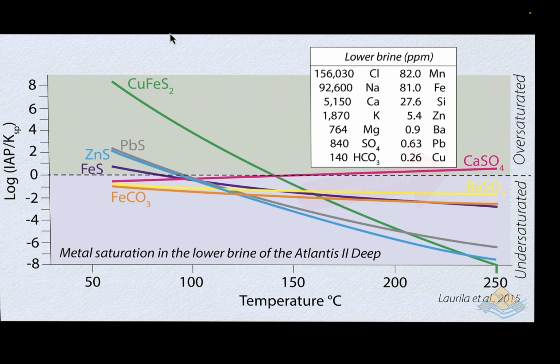Contrast with that is the calcium sulfate, the anhydrite curve. The calcium sulfate becomes more soluble at lower temperatures. It's a retrograde salt. And that's the reason for that inverse relationship between the presence of anhydrite, which indicates probably warmer temperatures, and cooling, when the anhydrite goes into solution and the sulphides accumulate. So this is the cooling effect driving the precipitation of sulphides in these hydrothermal bottom brines. This is not the redox interface effects we've been emphasizing as forming most of the world's red bed sedimentary copper. This is a different animal.